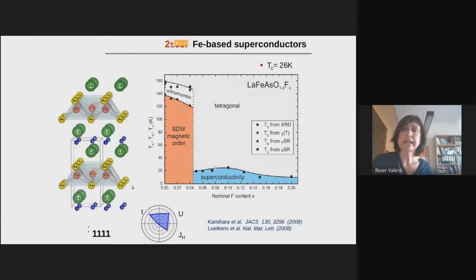And again, let's first look at the structure. They have a structure similar to the cuprates that I just talked about. Now what we have is planes of iron and arsenic, so the layers are not copper-oxygen, but iron and arsenic. And they are again separated by some cation species. And if we look at the behavior of the system, again I'm drawing a phase diagram, temperature as a function of doping. In the parent compounds, these systems are again magnetic.